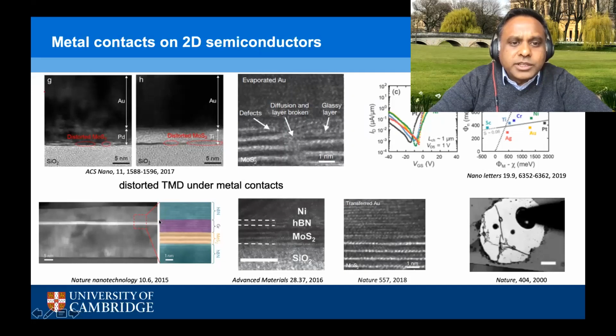This is very nice work done by Jim Hone's group a few years back, where they did mechanical transfer of graphene on 3-layer MoS2 and got wonderful results. As I mentioned earlier, one can use hBN as a buffer layer between the 2D semiconductor and the metal to prevent damage and reactions of the metal with the 2D semiconductor, and the hBN is sufficiently thin that it can facilitate tunneling from the metal into the 2D semiconductor.